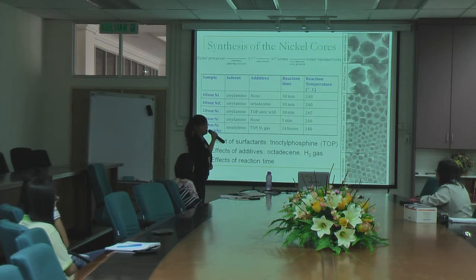Yes. For the cadmium selenide shell, how do you control that it can be developed only on the nickel particles? You mean... I understand what you mean. So the cadmium selenide has two choices. It either grows on nickel or it grows by itself. Actually, in my case, based on my reactions, I find both happen. So I have cadmium selenide that grows on the surface of nickel, as well as, because the amount of cadmium selenide that I use is always in excess, there's always some that grows separately.